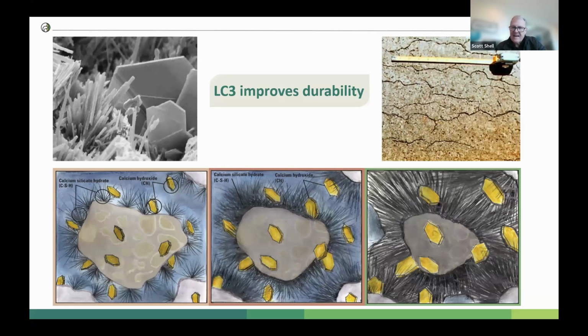But you'll also see these hexagonal shapes. That's calcium hydroxide. So that's kind of unreacted material. The SCMs actually react with that calcium hydroxide and make more of the CSH. So they complete the reaction of the CSH and make more of it. This also makes the concrete less pervious, so that less water can get into it. One of the primary mechanisms for degrading concrete is water getting into it through perviousness or cracks, degrading the rebar. That rebar then rusts and it expands and it cracks the concrete.